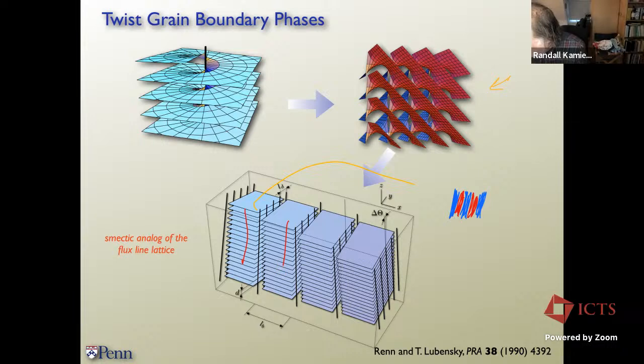And so now you have the next region over, where the lamellae are rotated compared to the old one. And you can accommodate that. I showed you yesterday how you can accommodate a set of layers with one normal, like so, and a set of layers with another normal, like so. You can accommodate them with Scherk's first surface. And you can do that smoothly, so that instead of having a place where you have to cut the whole domain, instead, you just have these helicoids. Each of these black lines is a helicoid.